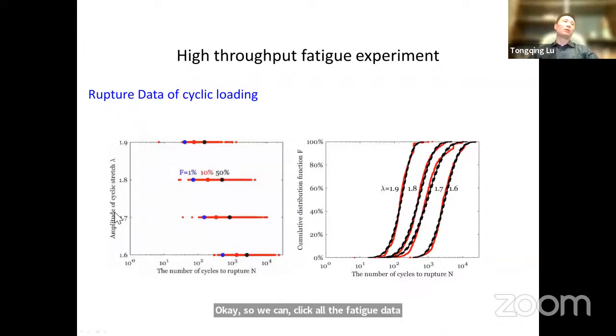First, we can plot on the traditional lambda-N plane. For a given lambda, you have many numbers of cycles, 1,000 points here. Because there are so many points, we cannot see the scatter very clearly. So we prefer to present the results on this CDF plane as a function of the number of cycles to rupture. Once again, this CDF means, for example, if you apply 100 cycles, maybe 60% of the 1,000 samples have ruptured.